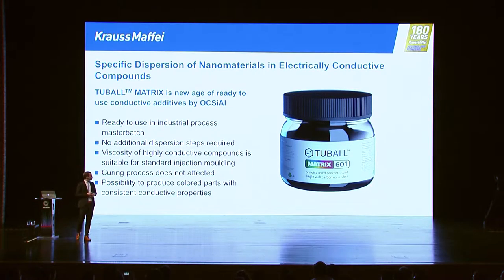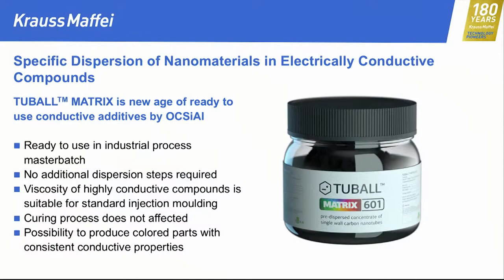The solution is the Tuball material. I hope I pronounced it right, sorry. Actually, the big advantage of this material is due to the single wall carbon nanotubes. It is possible to only put around 1 or 1.5% in the compounding with the LSR material. So 98.5% of LSR and 1.5% of this beautiful material, which does not have a negative effect on the processing anymore. There is almost no change in the viscosity, and also the final properties of the part are brilliant.